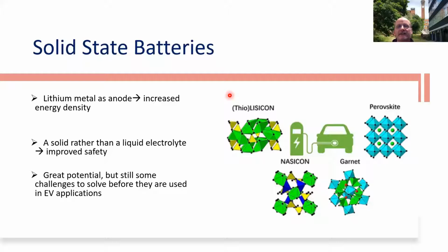If we could replace our liquid electrolyte by a solid, and a non-flammable solid at that, then we introduce inherent extra stability in the material, and you can start to think about using lithium metal as your anode. And that gives you much higher energy storage, because ultimately the key thing is the amount of lithium over the weight. Well, if you've only got lithium metal, it's the most energy density you could ever get for an anode.